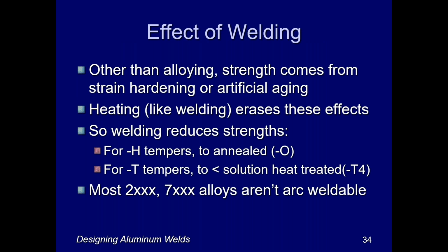Now, I mentioned earlier that when you weld aluminum, you typically reduce any strength that you got from tempering. And the tempering processes like strain hardening or artificial aging are used specifically to strengthen the aluminum from its base metal condition. And when you weld it, you wipe those out. So that's a big drawback in welding aluminum. And any kind of heating, for that matter, a fire, a paint bake cycle, can have that effect unless it's very controlled. And in the case of welding, the temperature is so high, it's above the melting point, that it's going to reduce the strength on either side of the joint, and that's inescapable.